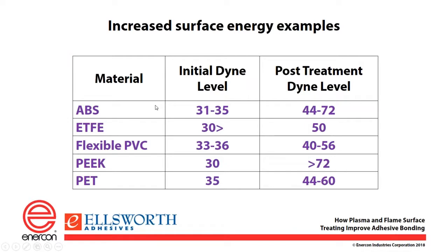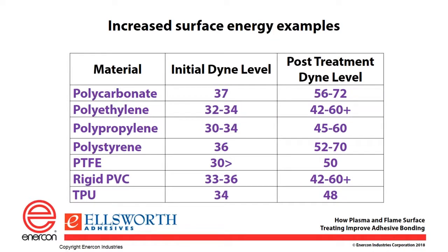Here are some examples of materials on the next 2 slides. Their initial Dyne is listed there in the middle. PEEK, for instance, starts out at about a 30 Dyne level. On the right, you're going to see a range of post-treatment levels. We can vary these levels based on the speed and the distance and the way we treat it, whether it's going to be flame or blown ion or blown arc.